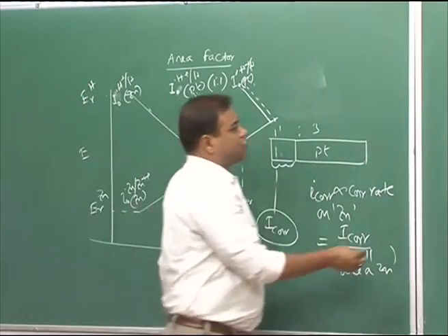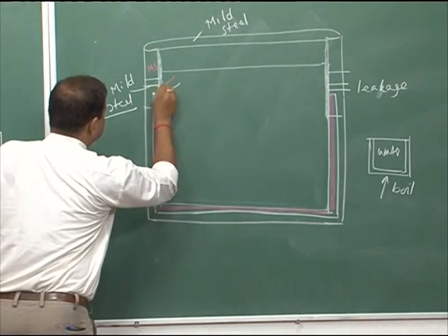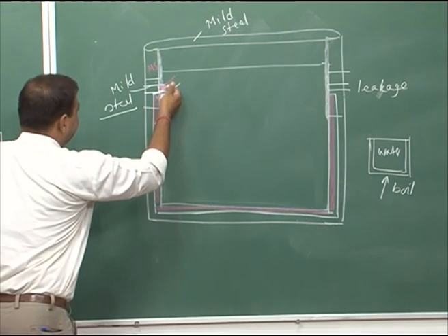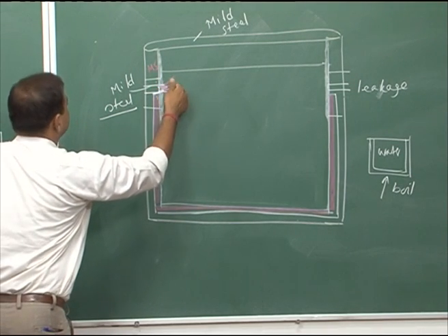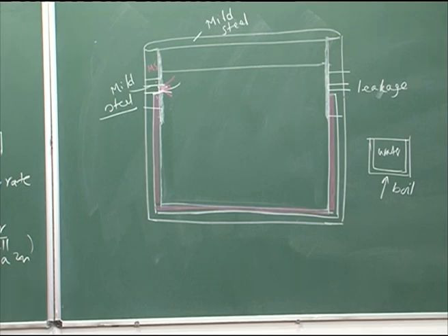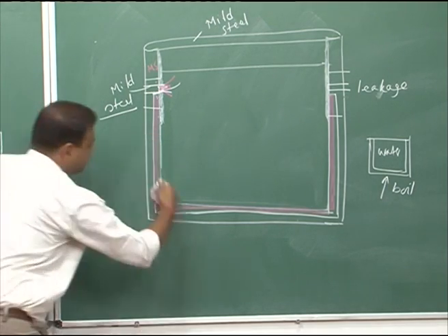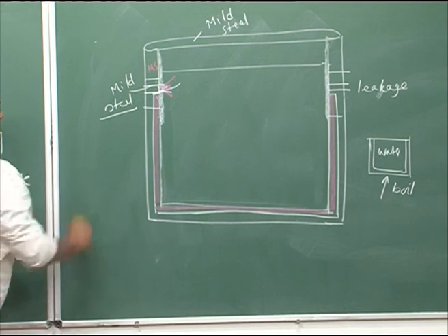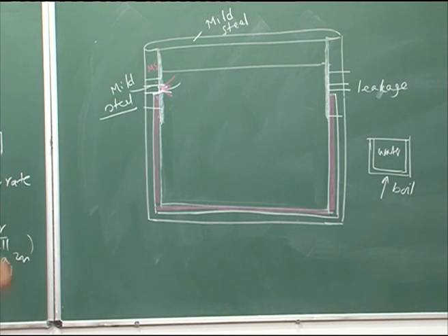So, the rate of corrosion at this zone would be manifold, and gradually this will dissolve and there would be leakage. This is also happening because we have a large exposed cathodic area and a very small anodic area. Now, how would we protect it?